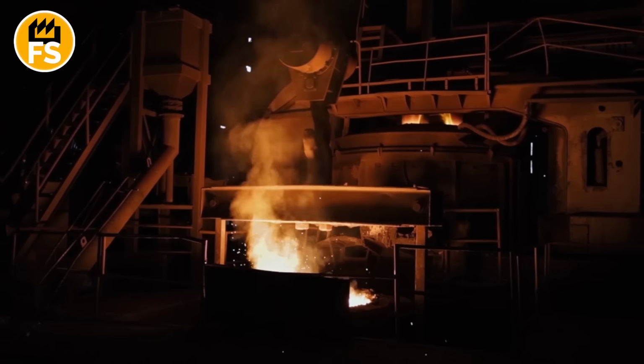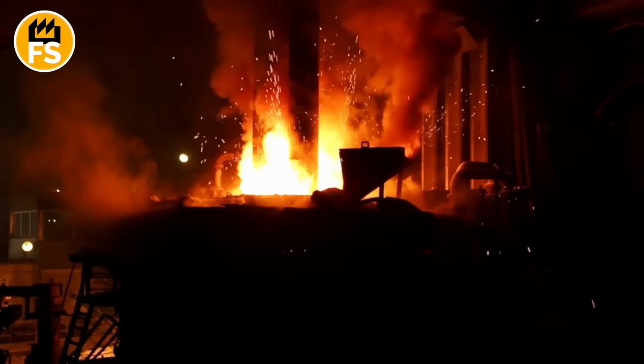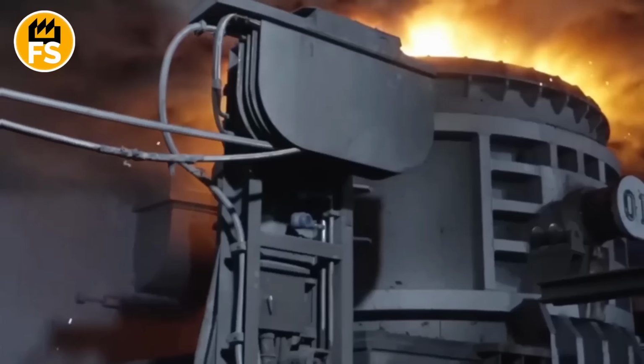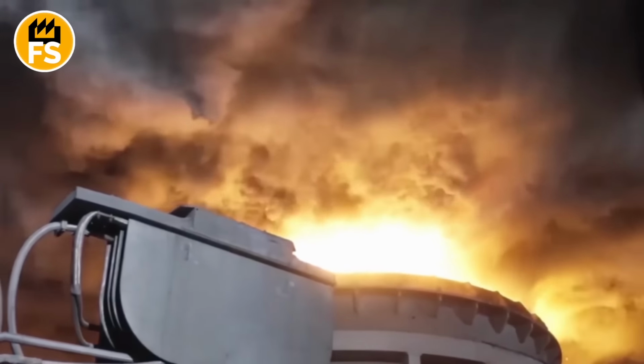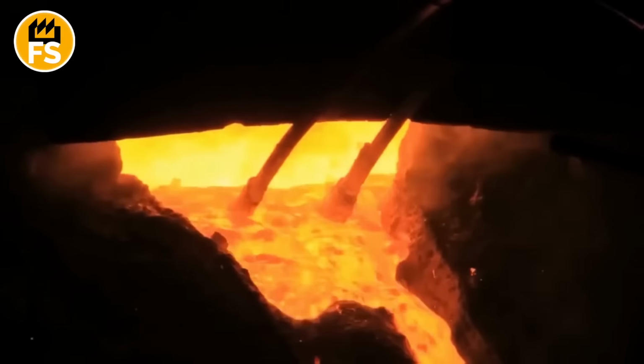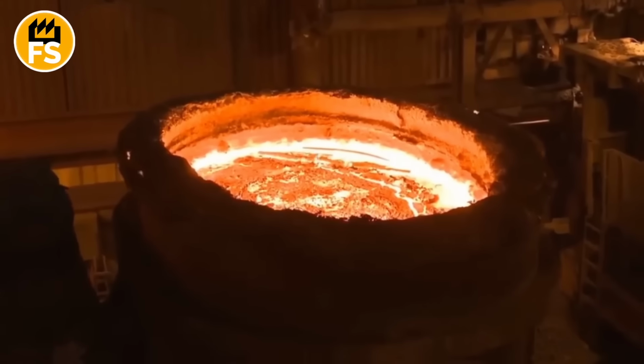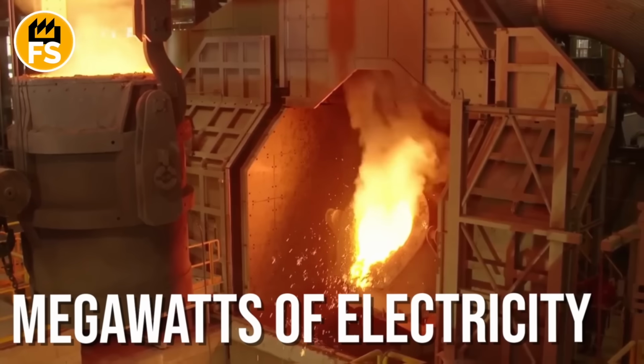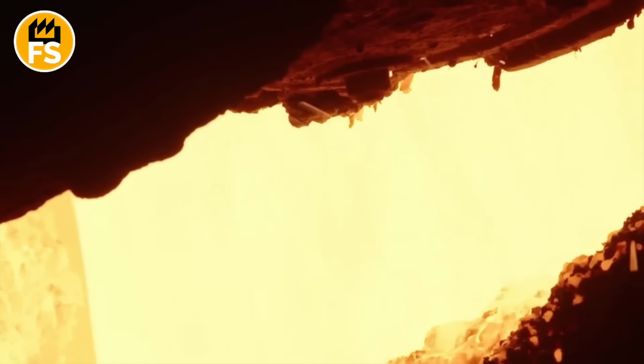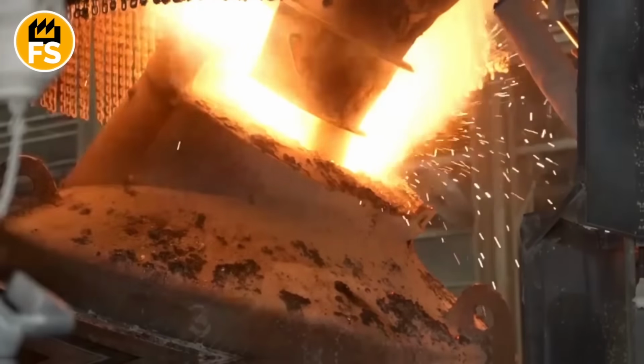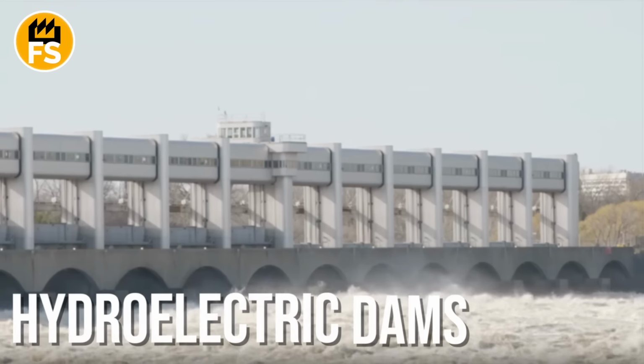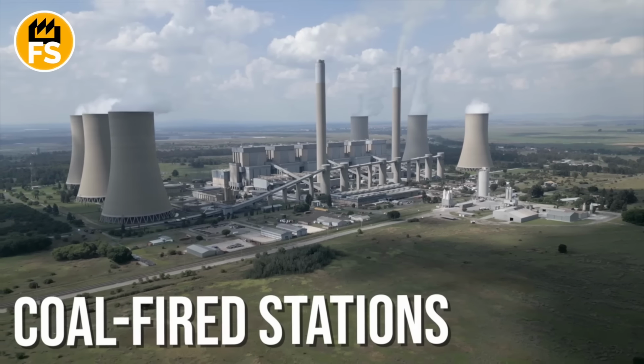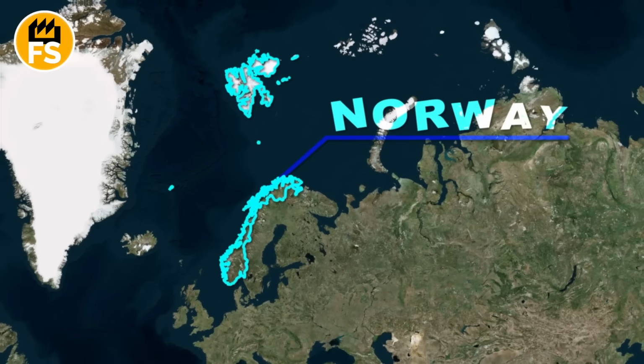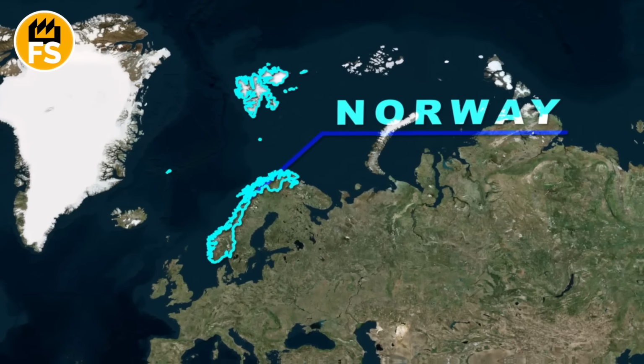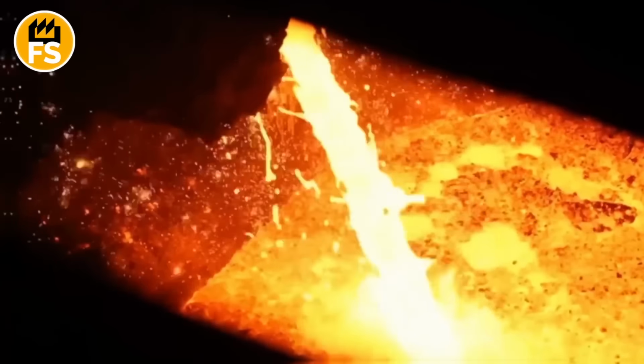Carbon reduces manganese oxide into metal. Molten ferromanganese sinks to the furnace bottom. Slag floats to the surface. Every few hours they open the tap hole, and a fiery river of metal flows into ladles. One furnace devours megawatts of electricity. That's like a small town. That's why ferromanganese plants get built near cheap power sources, hydroelectric dams, or coal-fired stations. Norway uses cheap hydropower, which is why Norwegian ferromanganese is considered some of the highest quality.